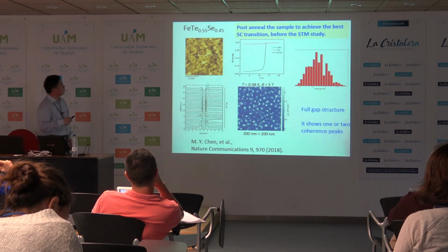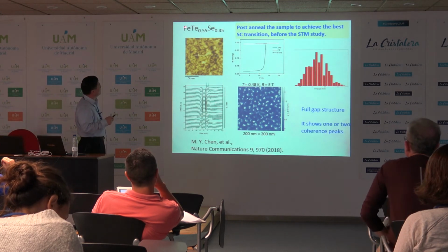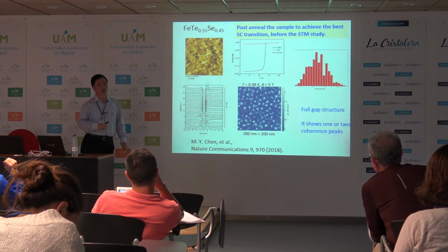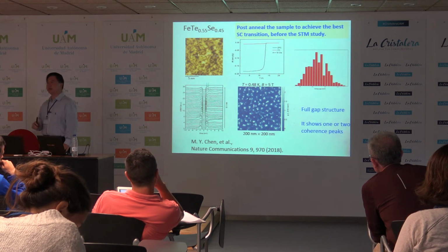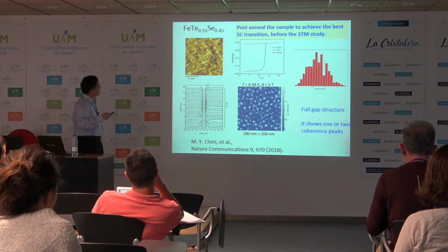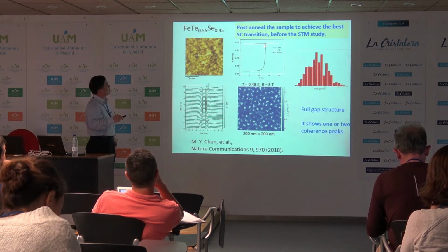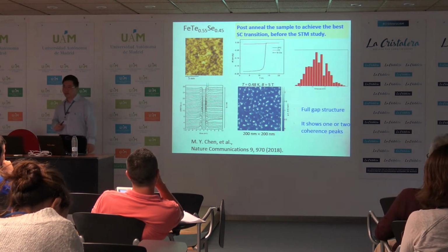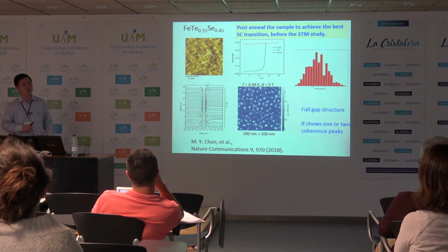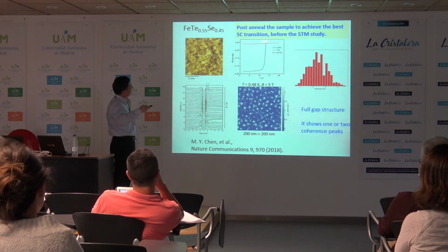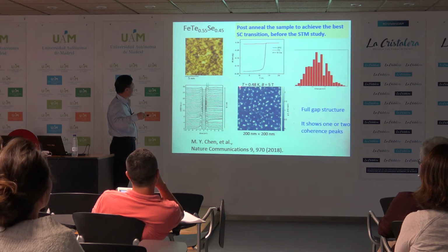We measure iron tellurium selenium. As you heard, in iron-based superconductors, the Fermi energy can be very comparable to the gap, as mentioned by Yuji. In my group, we always check with the SQUID, because we have the facility in the group. Before the STM measurement, we always check whether the quality of the sample is good. The transition looks quite good, and then we measure the tunneling spectrum.